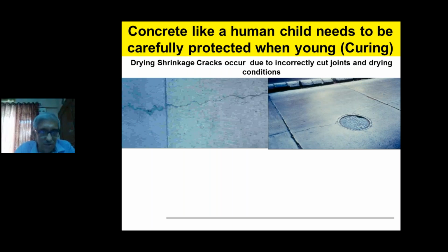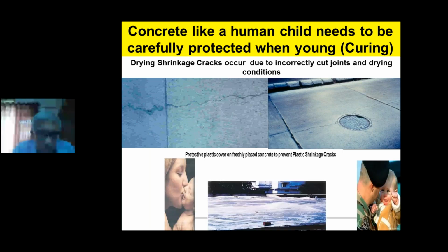Concrete, like a human child, needs to be carefully protected when young. And the best way to protect this young child, concrete, is by proper curing. Many a times people think that curing is only good in the daytime. And when the specification says you have to do 7 days curing, it is round the clock curing. Because drying of the surface of concrete also happens in the night due to wind, and therefore the strength is lost. Concrete can develop defects like drying shrinkage cracks at a later stage and plastic cracks during the early stages of concrete.